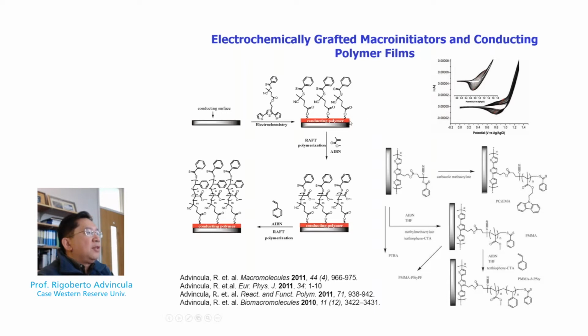Once we are able to graft this conducting polymer macro initiator on the surface, we can then polymerize, let's say, polymethyl methacrylate with the AIBN initiator, graft the polymethyl methacrylate, and since it's a living free radical polymerization method, we can then graft a second monomer, in this case styrene. So in principle, you have a conducting polymer macro initiator layer followed by a block polymer brush of PMMA and polystyrene. Okay, so we were successful in doing this.